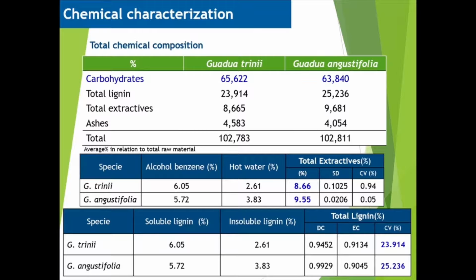We found that Guadua trinii has a total extractives content slightly lower than Guadua angustifolia, almost 1%. Ash content was similar for both species, around 4%. Total lignin content was similar in both species, almost 24% for Guadua trinii and 25% for Guadua angustifolia. The total carbohydrates content was almost 66% for Guadua trinii and 64% for Guadua angustifolia. A summative analysis was carried out in which both species have a total percentage of components of 102%, which is encouraging because being close to 100% validates the characterization carried out.